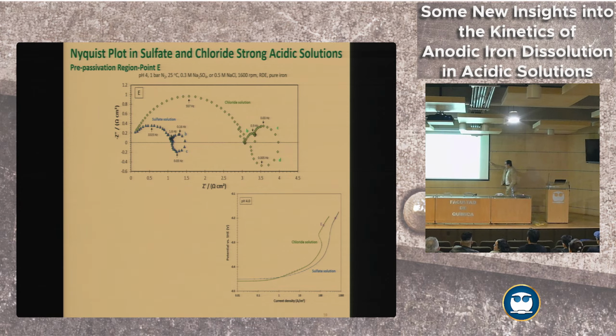You're talking about the low frequency. No, not the values in frequency, but in impedance. Oh, okay. In the real axis, yes, those values are really small. So the corrosion rate should be very high, and we are in the anodic branch, that is right, but we are at the pre-passivation point. So I would expect this value should be higher, not 1 ohm centimeter squared.